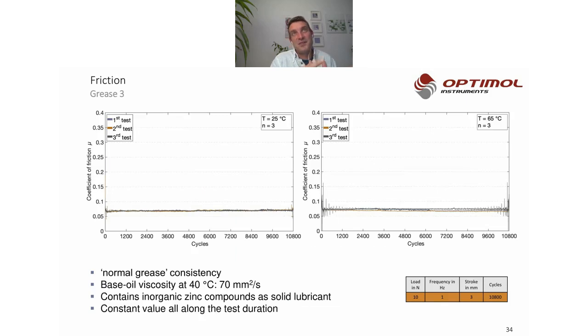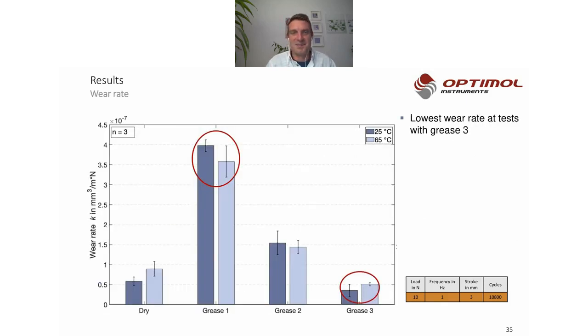And then, besides friction, you need to have a look at the wear behavior, and that was very exciting and fascinating. As you can see here, we used this mixer tap without any grease, because there was the idea that maybe these ceramic coatings are good to go without any lubricants, and we ended up with very low wear rates for the dry contact. What nobody expected is that if you implement a not so promising grease, one which will not work with these surfaces together, you end up with much higher wear rates. And it's unexpected, let's say.